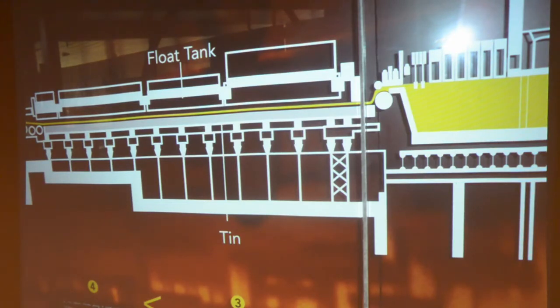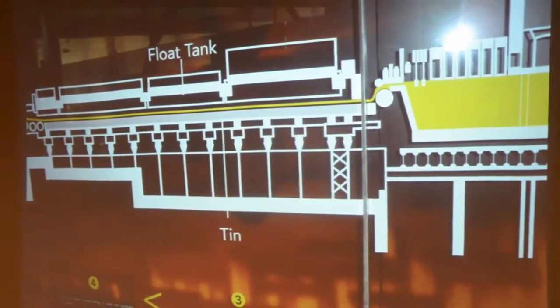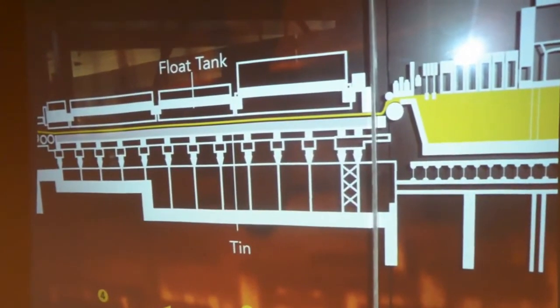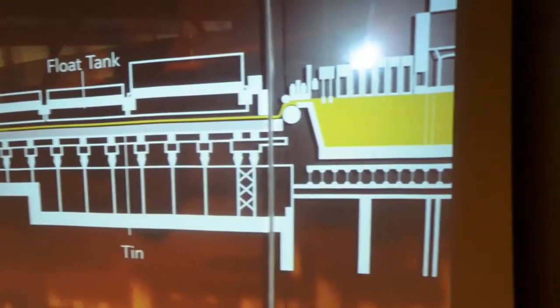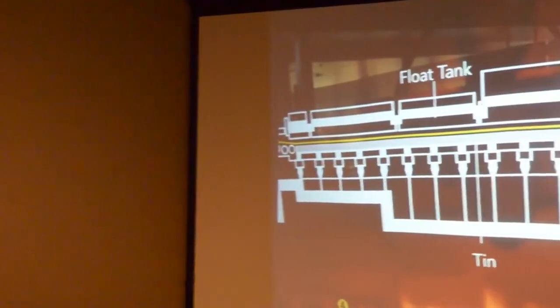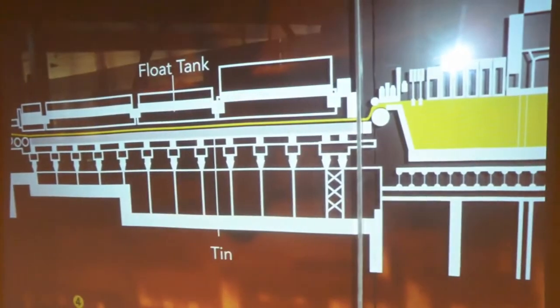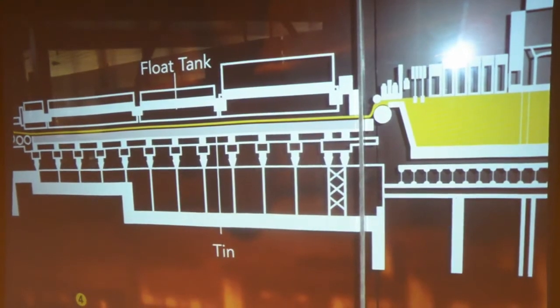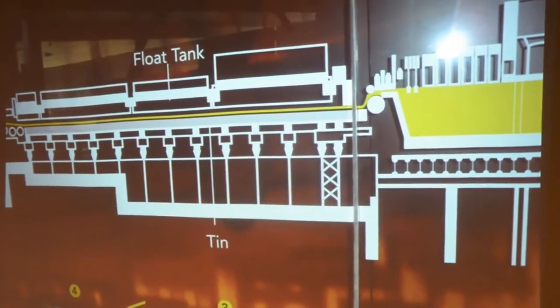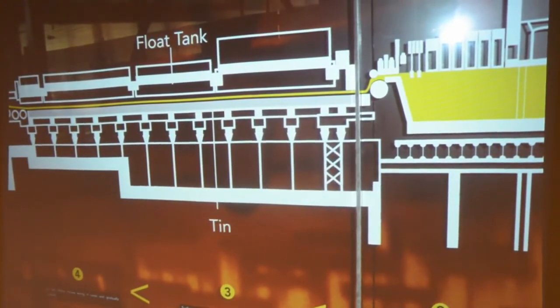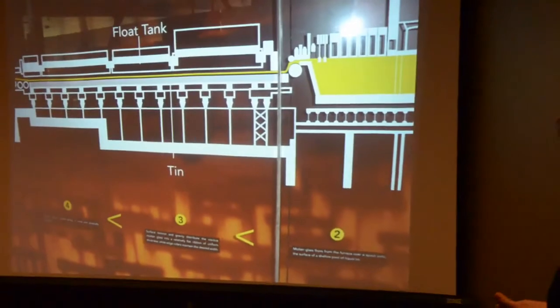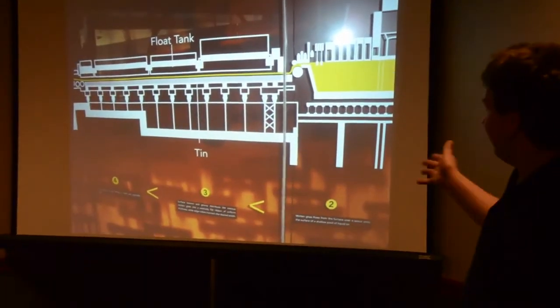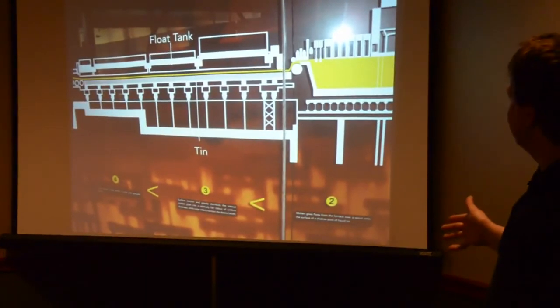But I tried this at home too, because I just wanted to be able to learn to do everything. And the first time I heated up the tin bath, the tin oxidized. It turned into this nasty white crud. And I said, well, yeah, that's what liquid metals do when you sit for hours in an oxidizing atmosphere. And looking through the literature, I found out they don't quite use an inert atmosphere of argon. They use a hydrogen-nitrogen mix. And that was a pretty neat thing to learn. The extra hydrogen at high temperature will attack any oxygen. It'll form some water vapor, it'll clean the atmosphere so that you can save a lot of money and have it mostly nitrogen that way. Very important savings when you've got this float bed that is that long.